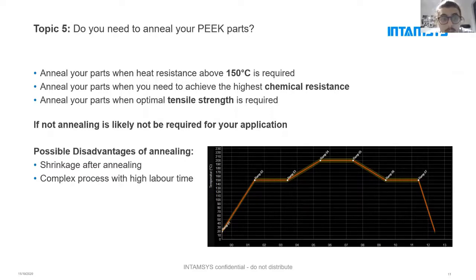Second point, anneal your parts when you need to achieve the highest chemical resistance. Due to the increased density and the change of the chemical structure of the polymer, a crystallized or annealed part has definitely less porosity in the structure, which gives you in the end a higher chemical resistance. Still, amorphous parts have a good chemical resistance, but definitely a little bit less than an annealed, so a crystallized part. If you need the highest tensile strength of your parts, especially in X and Y axis, then you also should consider if you anneal your parts.